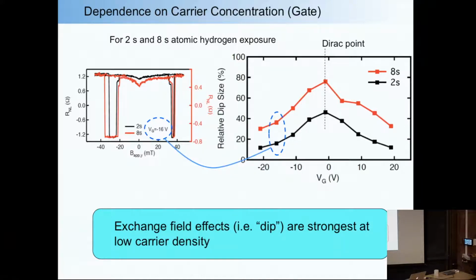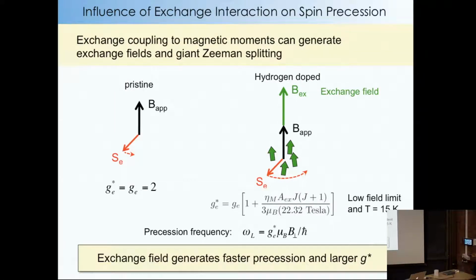I want to tell you that all these measurements were done at a particular carrier density, and it turns out that if you change the carrier density, the relative size of the dip can also change, right? This is for 8 seconds of hydrogen exposure. This is for 2 seconds, and both of them show a peak. So this exchange coupling effect seems to get strongest at charge neutrality, at the Dirac point. Okay, I'll come back to this in a few slides. The other thing that's neat is that if you have these magnetic moments, you can generate an exchange field, and this is something that we've been wanting to see. The idea is that not only do you have the external field, but you have the coupling of the electron spin with a magnetic moment, and it will create something that looks like a large field. So you'll have the regular field and the exchange field, and you add them all together, and people like to talk about this in terms of an enhanced g factor, so it'll precess faster.